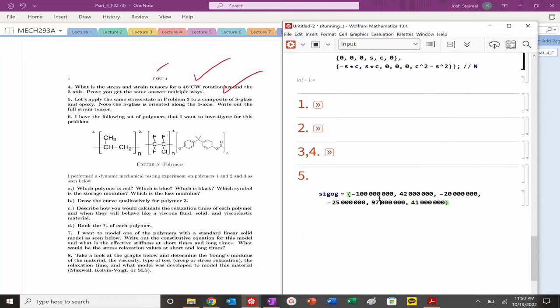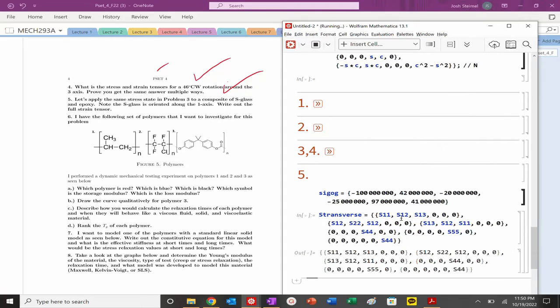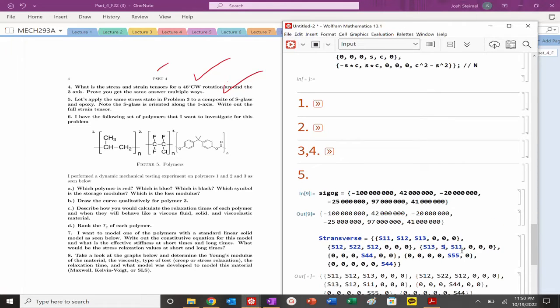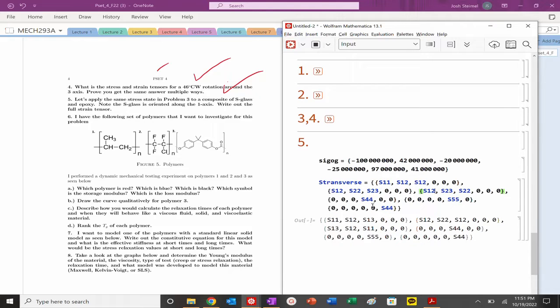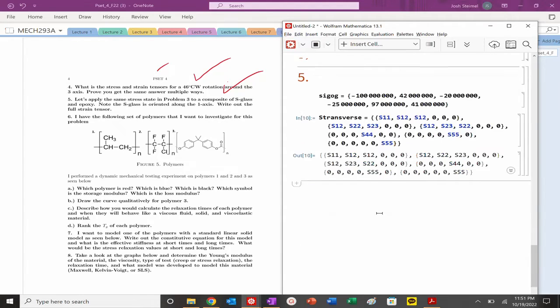If fibers are oriented along the 1-axis, S11, S22, and S33 need adjustment — S22 equals S33 for the transverse isotropic plane. The 2-3 plane is now the unique plane, so S23 is the unique Poisson term. S12 and S13 are equal (non-unique). S44 is the 2-3 direction — the unique shear — and S55 equals S66.